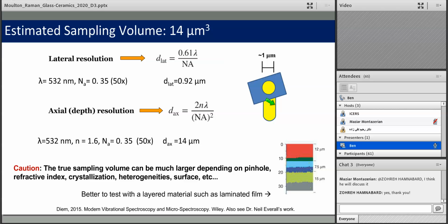So volume, if it's important, or depth resolution, if it's important to you, I recommend getting a laminated film and testing based on your experiments how deep you can see in which of these materials. And you can play around with the pinhole and the surface of your sample to improve this resolution. Generally, smaller pinhole, smaller refractive index, the better resolution you'll have.